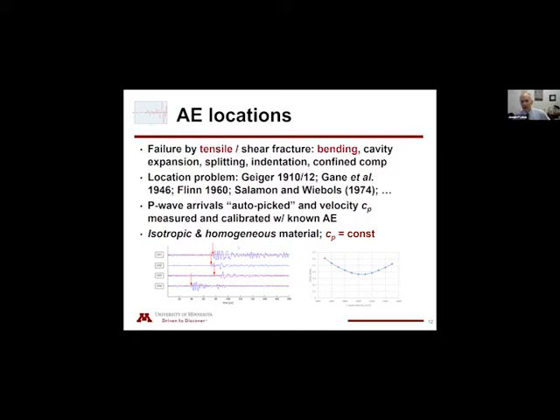smoothed by a procedure where we generate an event at a known location. So of course, an artificial event, we break a capillary. We know that location and we can adjust the wave speed to reduce the error to the smallest possible value. And then we would use that velocity in our location algorithm. We typically do not update the velocity.